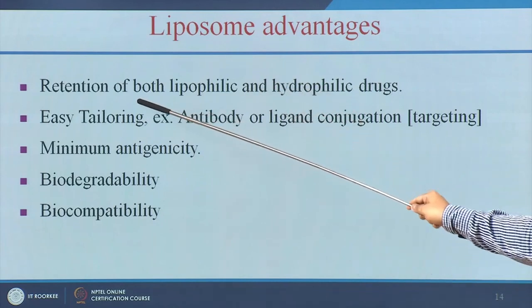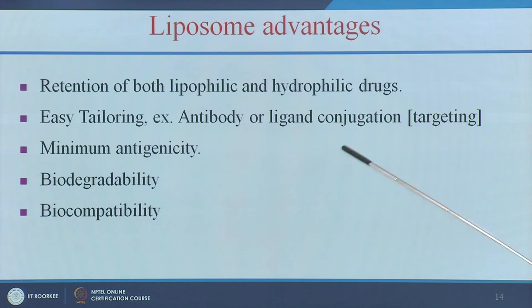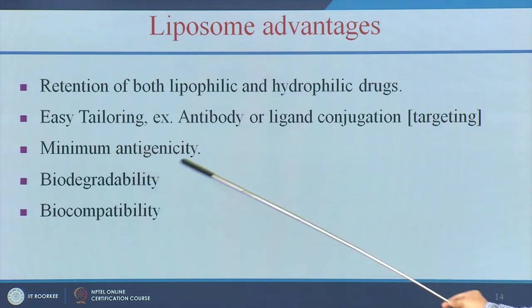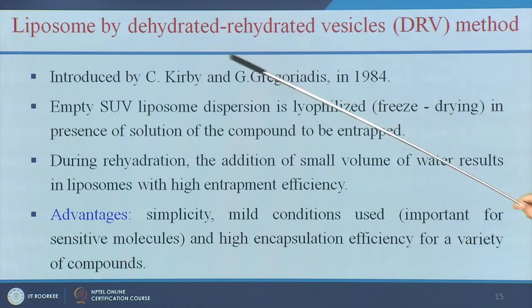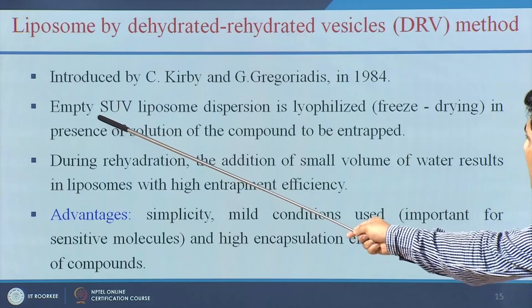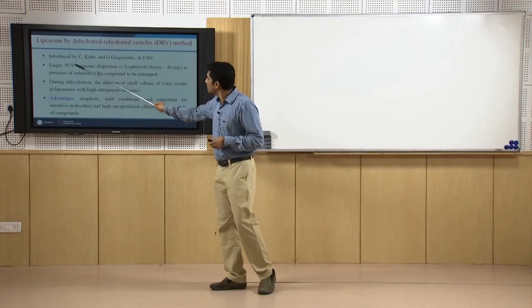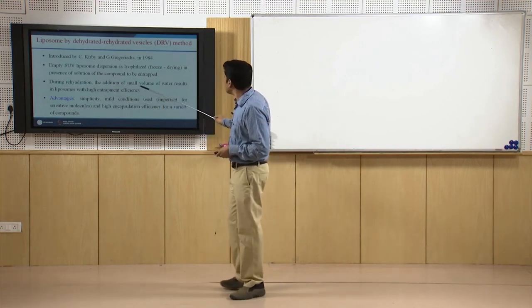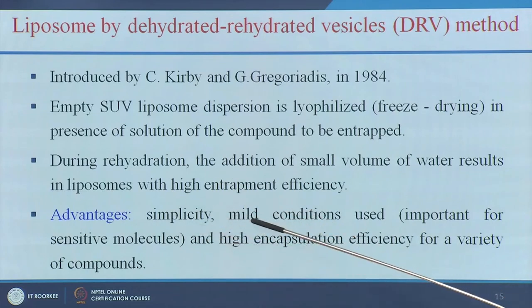The advantages of liposomes include loading both hydrophilic and hydrophobic drugs, easy surface modification with antibodies or ligands for targeting, and low antigenicity — meaning they are highly biocompatible and biodegradable. Liposomes can be prepared by several methods. The DRV method — dehydrated and rehydrated vesicles — involves lyophilizing empty SUV liposomes in the presence of the compound to be entrapped. During rehydration, adding a small volume of water results in liposomes with high entrapment efficiency.